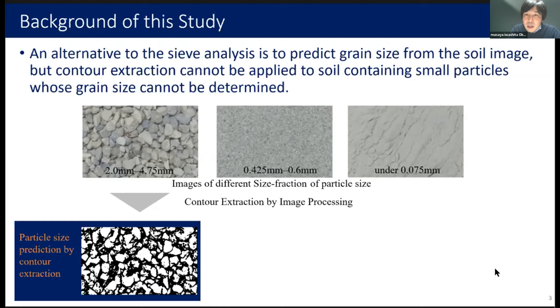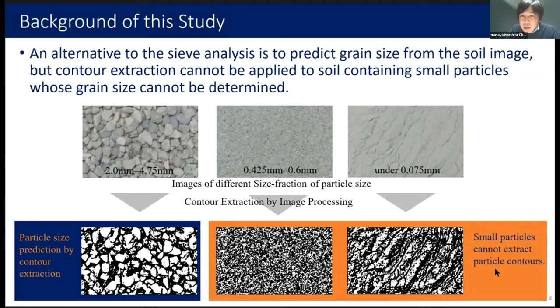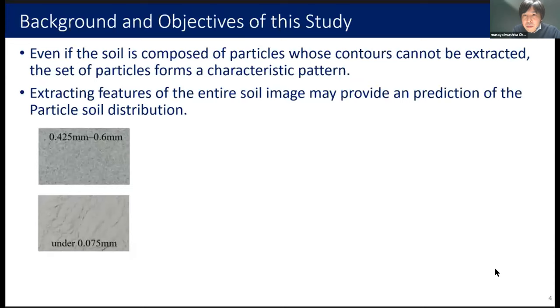But those in the particle size range of 0.425 mm to 0.6 mm and less than 0.075 mm did not have their contours extracted even with image processing. However, it can be seen that the sets of these small particles provide the soil surface with unique character.